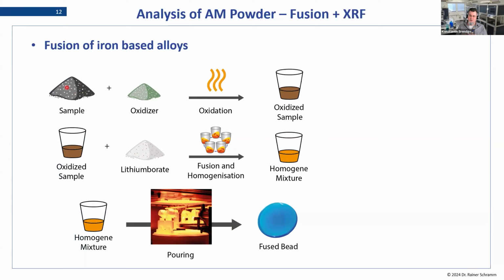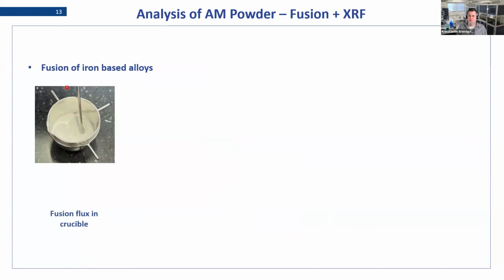The fineness of the powder here is very important. If you go above, I think it was 100 micron, you get into trouble because the oxidization is not really working. So, some more details: we have 600 degrees for the oxidization, and then around 1200 to 1250 degrees for the fusion. We do have some step by step pictures on how the recipe worked.